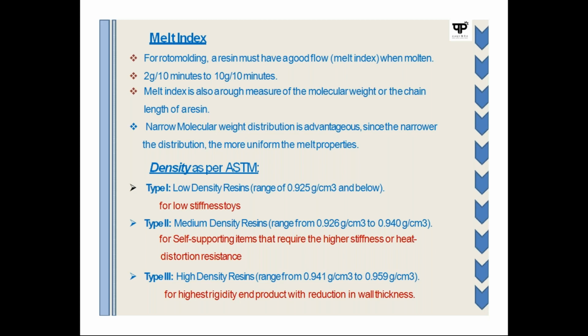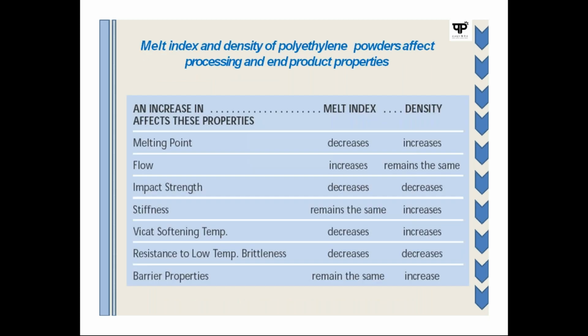The third type is HDPE, where high density polyethylenes are used, and sometimes HMW-HDPEs are also used, high molecular weight, high density. There the density you prefer is 0.941 to 0.959. These are used for high rigidity products. Suppose you want to make a 10,000 liter capacity tank or more than that. In that case, the type 3 material should be preferred in this application.